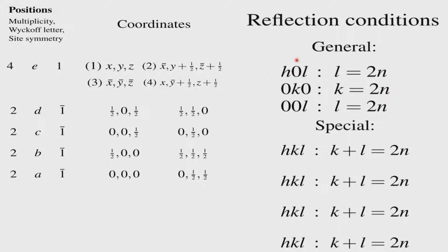These projection reflections can put additional conditions as though they are coming on the actual reflections, which is a special case of this. Then 0k0 will be the systematic absence due to the presence of the screw axis. Now, there is something interesting happening here. Apart from the 2 1 by c absence, we get additional systematic absences with respect to each one of these.